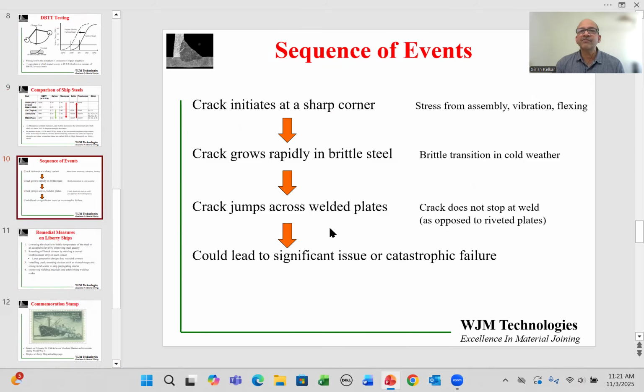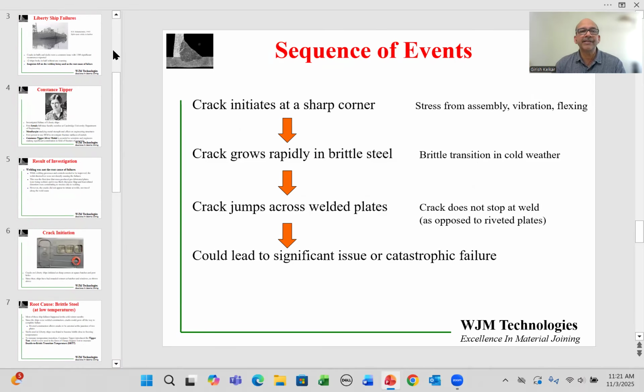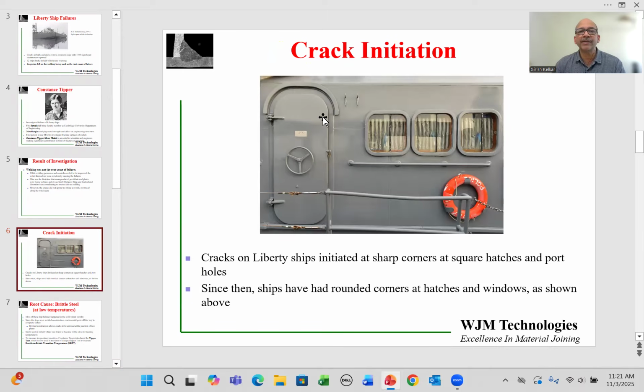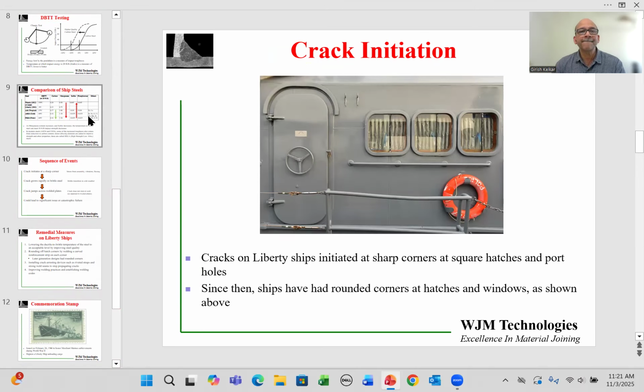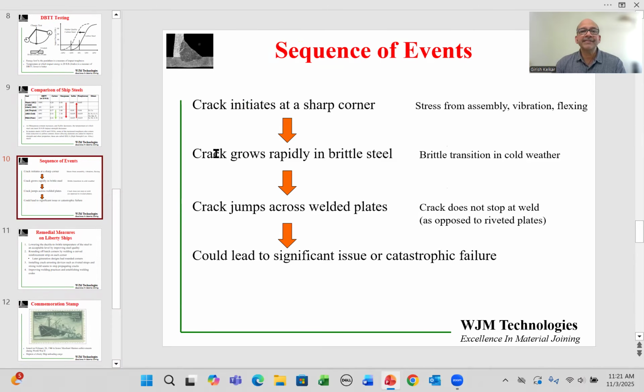So what was the sequence of events in Liberty ship failures? First and foremost, we have to have a crack which can grow, and the cracks would initiate at sharp corners, and these typically ended up initiating around these square hatches and ports. The second thing is cracks had to grow rapidly, and for that we needed a brittle steel. At low enough temperature and cold weather, the steel would become brittle. And once the crack initiates, the crack would grow very rapidly.